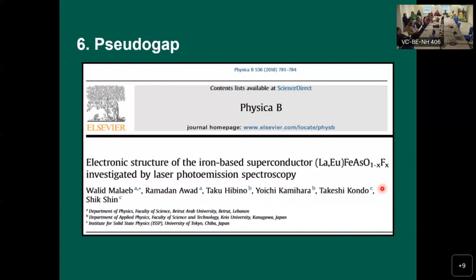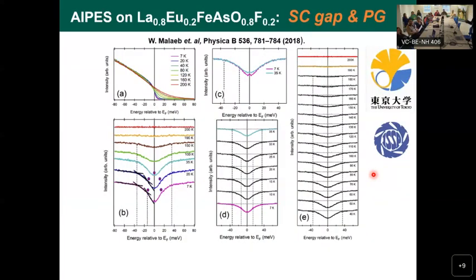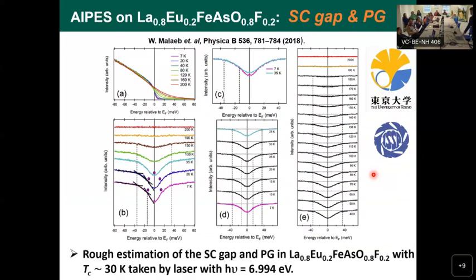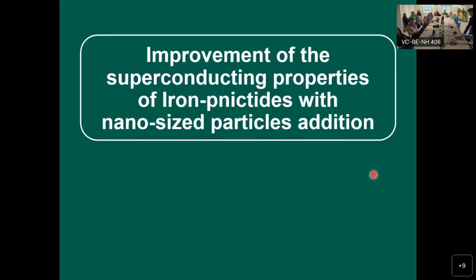We did this work also with Kamihara, the discoverer of iron pnictides, and we investigated a new sample, a new system, and we investigated the pseudo gap, this gap at room temperature. And again, we are sure that we have a pseudo gap. So pairing starts at high temperature, but somehow it doesn't lead to superconductivity. That's also important information, to know where to look regarding these materials. Well, I think that's about the photoemission part.